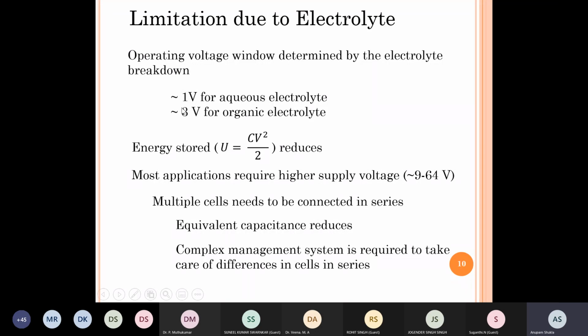Okay, so some people have now added to the organic electrolyte to expand the voltage window to 3.5, close to 4, but that is still smaller than most applications require, from 9 to 64 volts. If we are talking about EVs, they require 48 to 64 volts, and that has to do with the fact that most of these things run on DC current, and